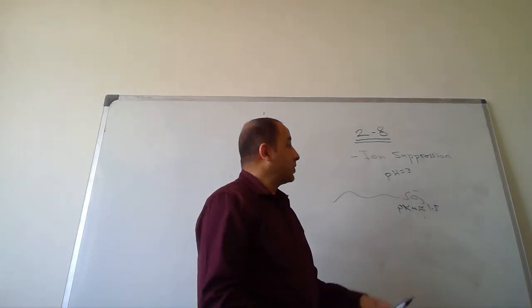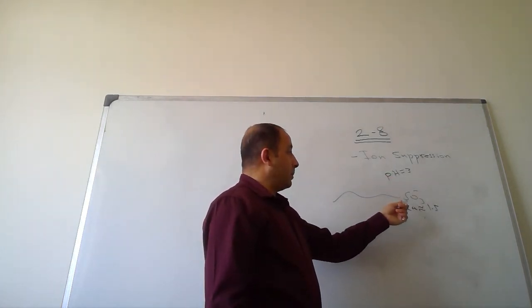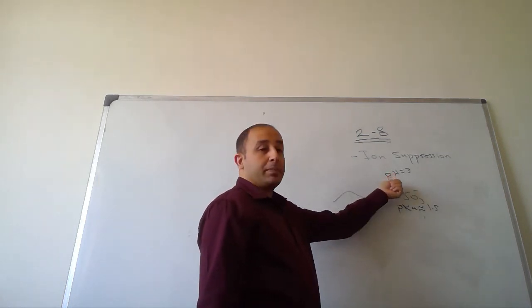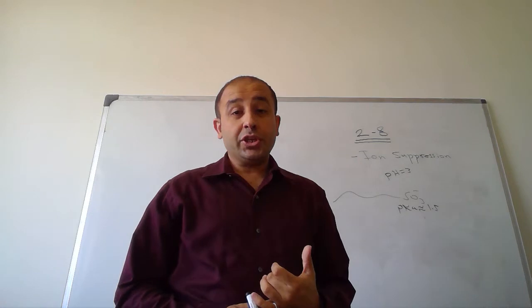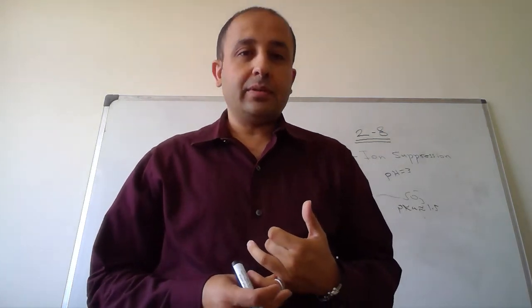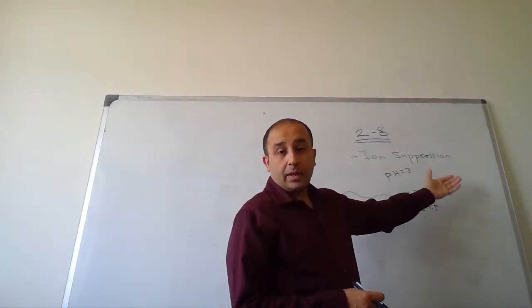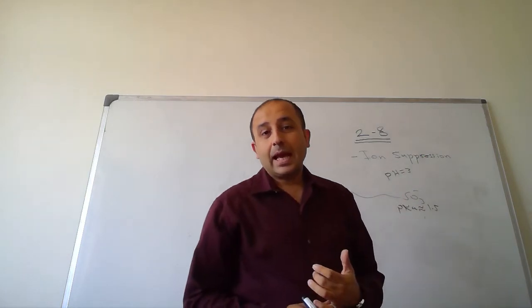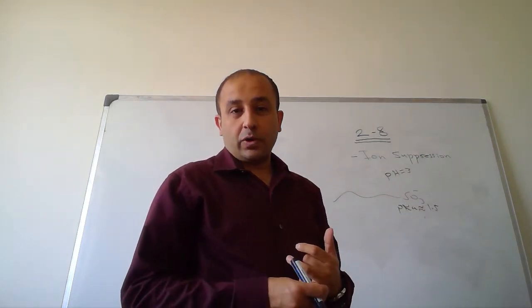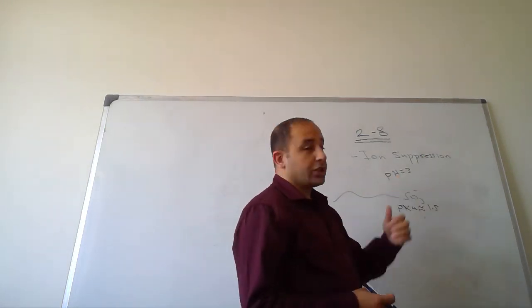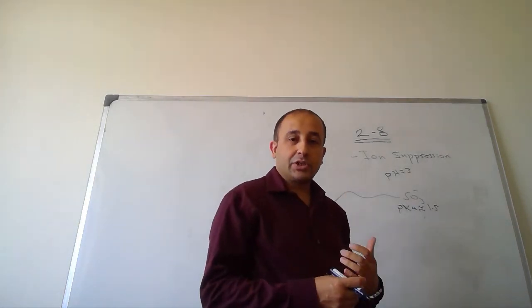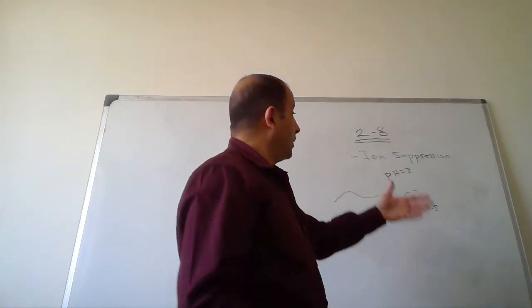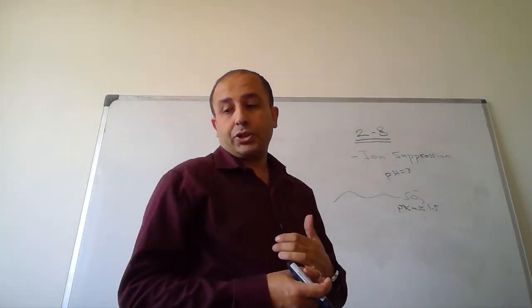So we can use ion pairing. We can guarantee in this case at pH 3 that sulfonate is still working as a detergent, as an ion pairing agent. And the same thing, the basic compound, of course, will be in cationic, ionized form at such pH. So we can mix more than one strategy. And also we can use end-capped columns with these conditions.